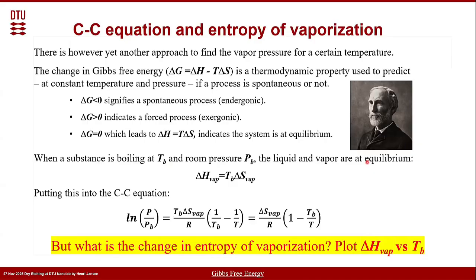entropy of evaporation. So putting this now into the Clausius-Clapeyron equation, we then get that the natural logarithm of the pressure, we now do it correctly, we divide it by the boiling pressure. So this is really a number and not a pressure or a logarithm of a pressure. It is the entropy of evaporation divided by R times 1 minus the boiling temperature divided by the temperature we try to find our vapor pressure. Good. We have replaced our change in enthalpy by the change in entropy. You should say, big deal. Now we still don't know it.